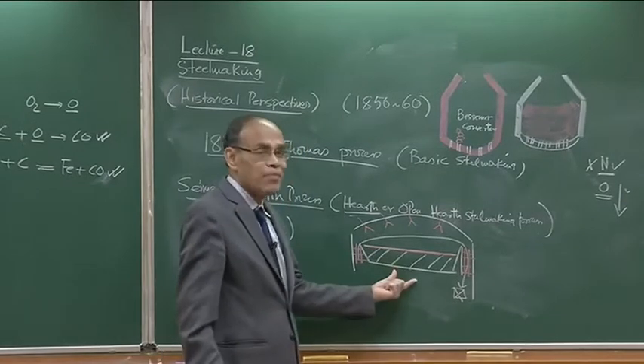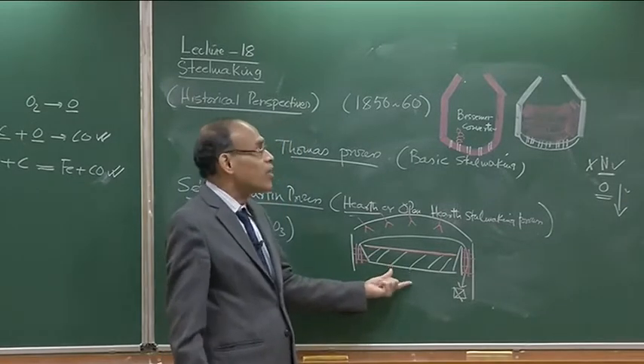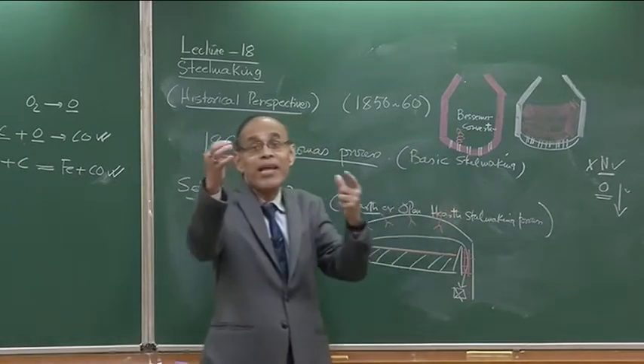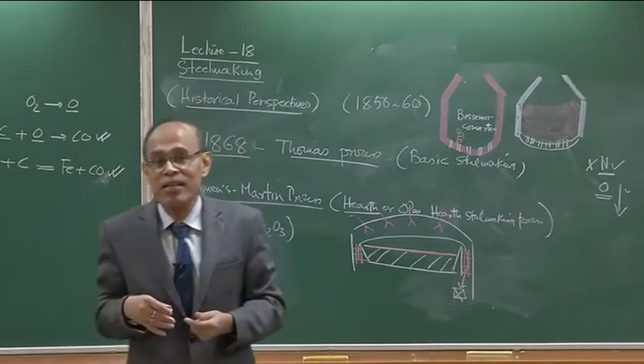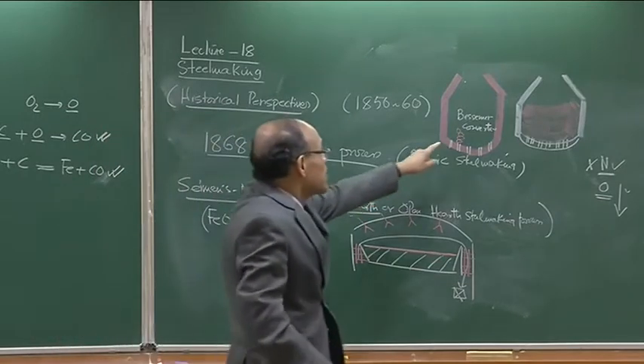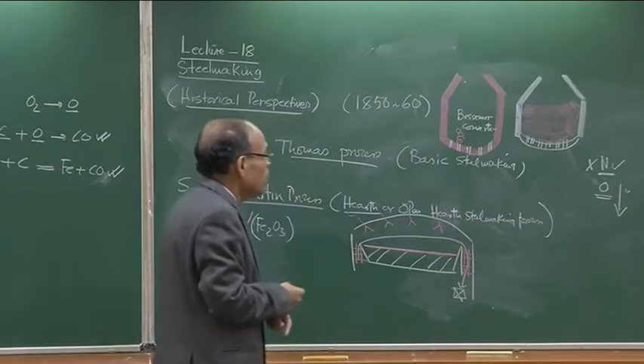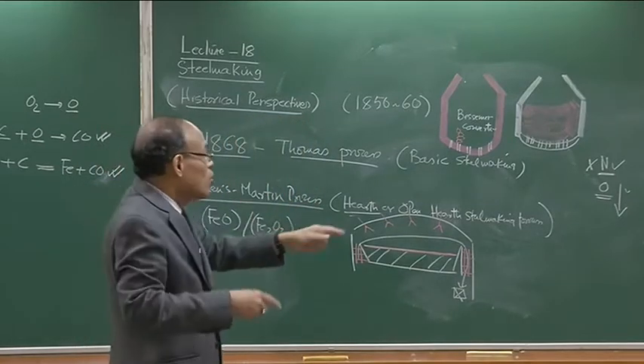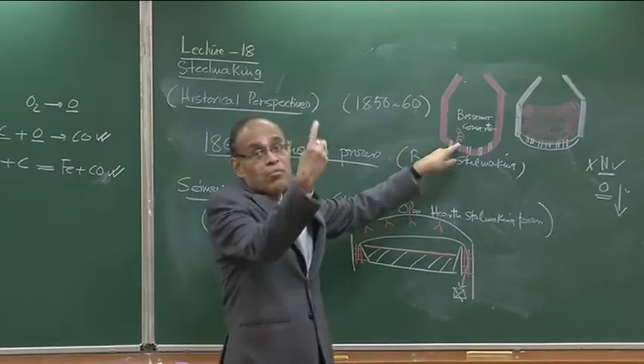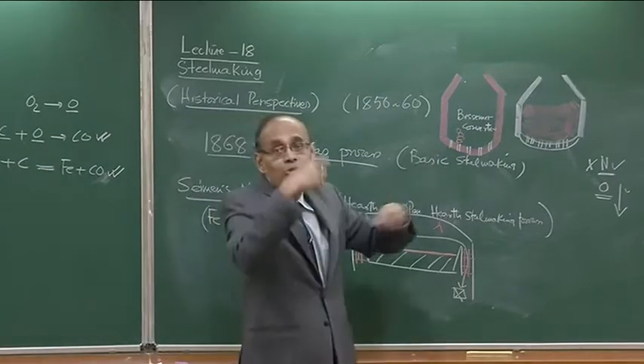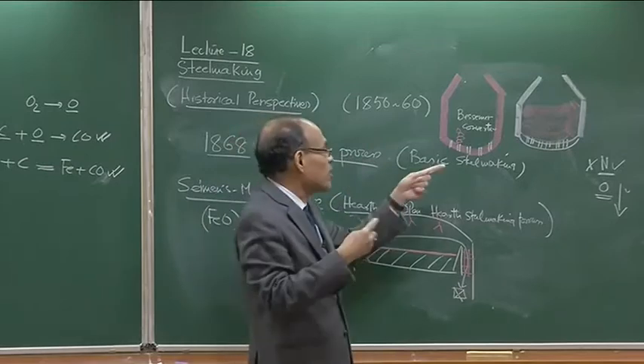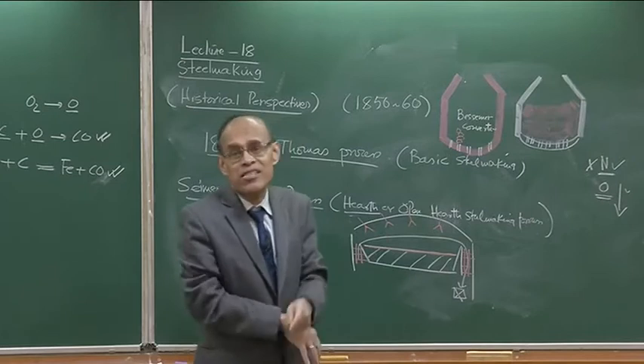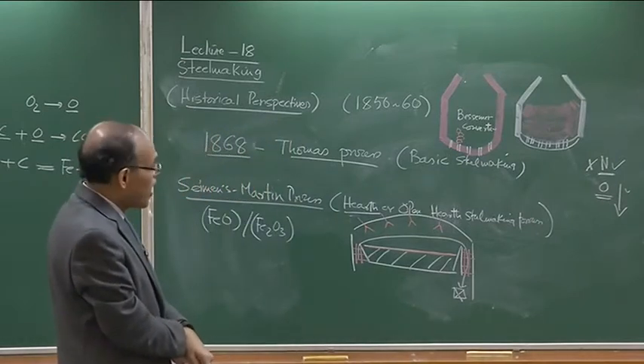Because nitrogen is not directly contacting the melt and oxygen is not blown in, you can produce very good quality steel. The open hearth steel making was producing better quality steel than the Bessemer converter. But the Bessemer converter was making steel much more rapidly because the gas-metal reaction was extremely quick — there is an intense amount of stirring when you blow gases through the bottom, leading to extensive slag-metal and gas-metal mixing that expedites chemical reactions between phases.